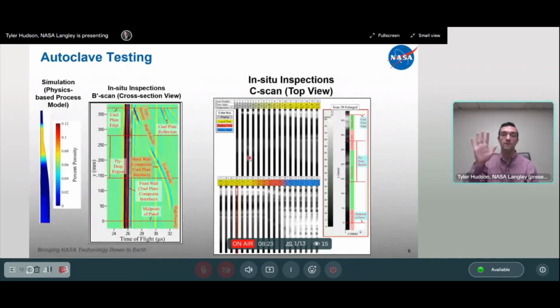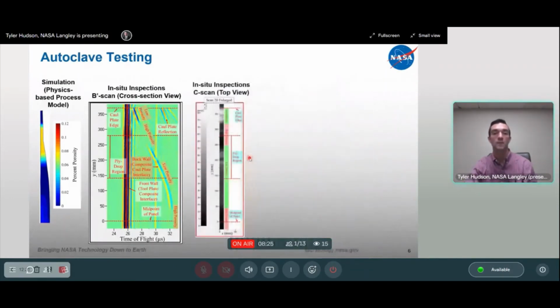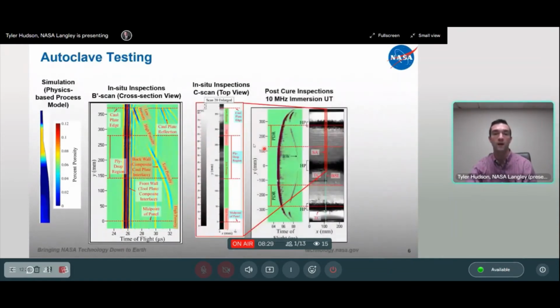We also can get top views of your laminates. Again, the through thickness and the top view line up. We can compare this top view to existing commercial UT systems after cure. So this is what's primarily done on composite structures right now after cure. And then we also took the same laminate and cut it.